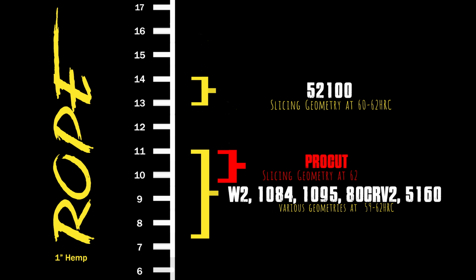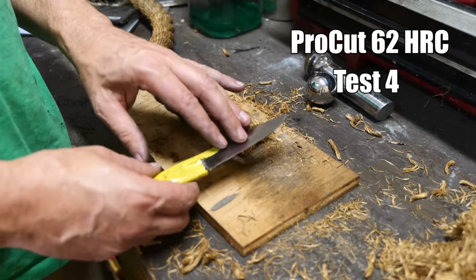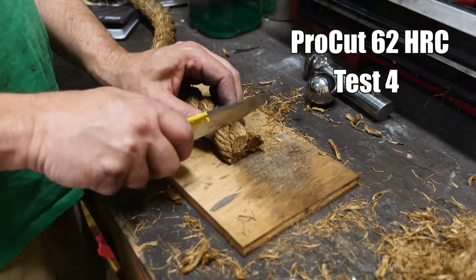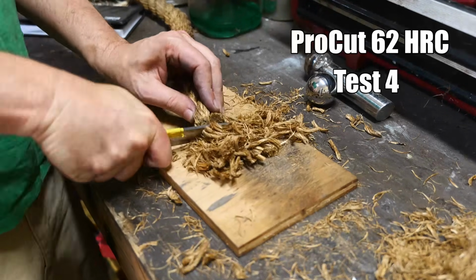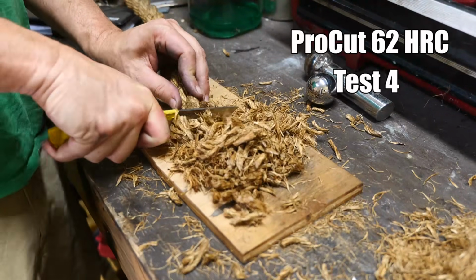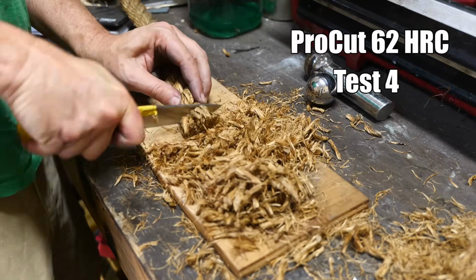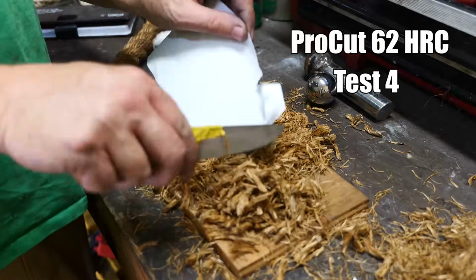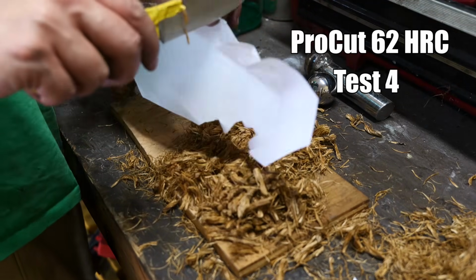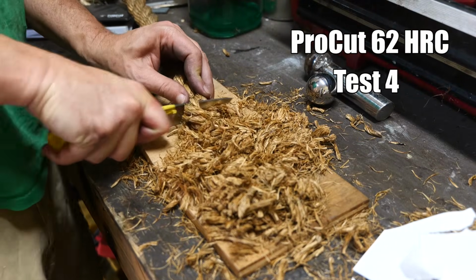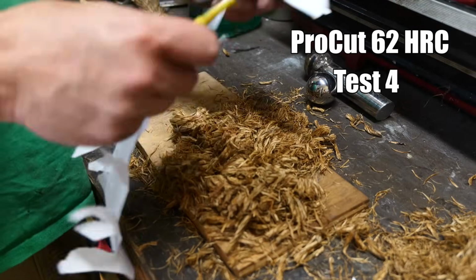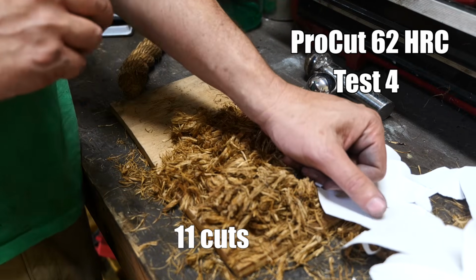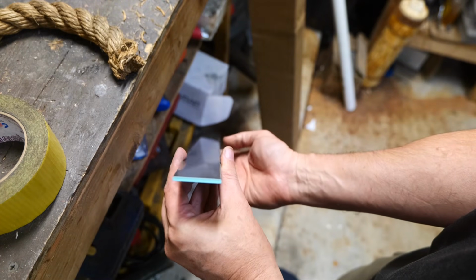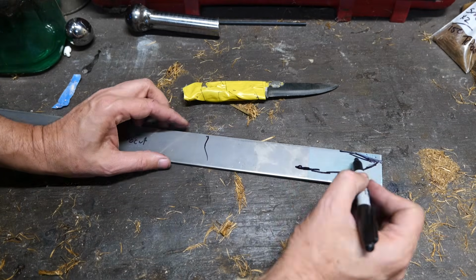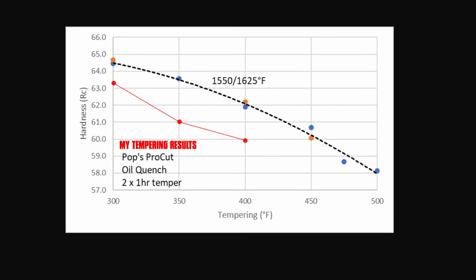My buddy who gave me this steel, I called Pops to report the softer tempering results and middle of the road edge performance, questioning whether or not he was sent the correct steel. He was told he was, and that it's likely a result of decarb along the edge, as if I've never heard of that. Anyway, I ground this back several millimeters just to prove that that wasn't the issue. The performance is identical. So I ordered my own piece of ProCut, and heat treating yielded the same temper curve, 2 HRC points lower than this graph.